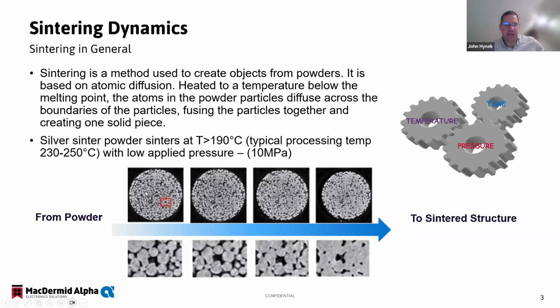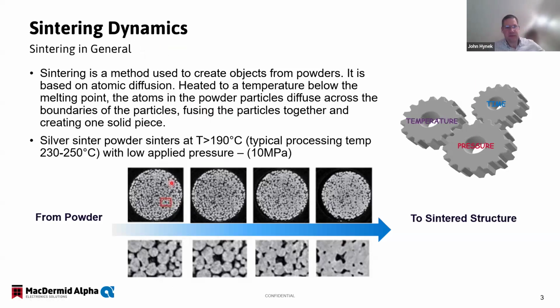And what happens during that time, when you have all your components and your sinter material at temperature, is that the organics are removed and the silver particles begin to, let's see if I can get there, there we go. You can see here the silver materials start to sinter or diffuse into each other, and then the grain boundaries become larger and larger. So you go from many small silver particles to a uniform area with some porosity, not much. Usually we aim for between 10 and 30% porosity. At first it seems like, wow, that's a lot of porosity, but that allows for some compliance and helps with the CTE mismatches between your components. So it acts as a stress relief between the components that you are sintering together.